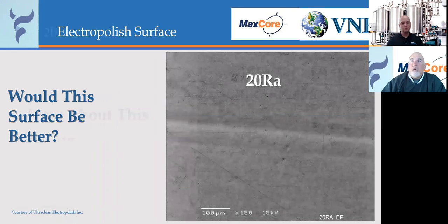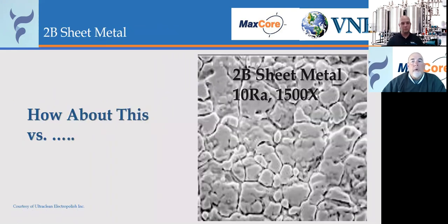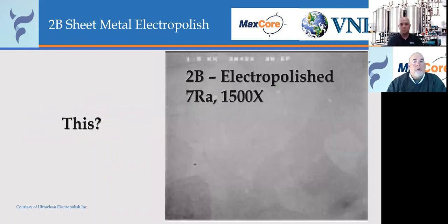This is a 2B sheet metal, 10 RA. You can see the grain boundaries pretty well. This is at a 1500 magnification. If you look at a 2B electropolished surface at 1500X magnification, all those grain boundaries have been reduced and smoothed out so that you no longer see that.